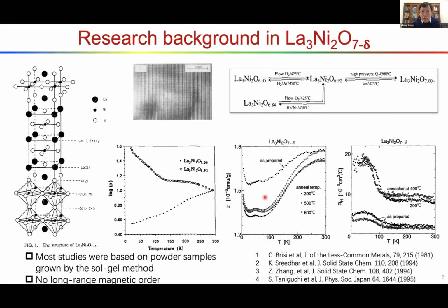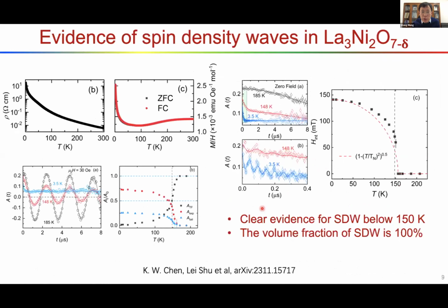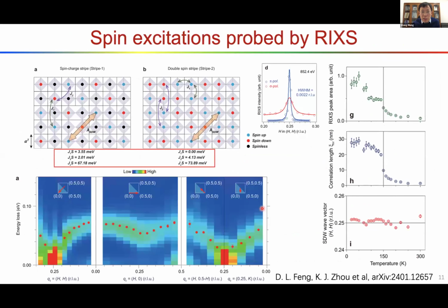People use this sol-gel method to grow thin crystals. Using this method, we can get powder samples with fewer oxygen vacancies. And actually, Professor Jin Changqing's group observed superconductivity on those samples. Yeah, but I'm just wondering whether the bulk susceptibility versus temperature still looks like what these old data look like. If we measure the sample at ambient pressure, it's very similar. But at high pressure, we don't know. Jin's group can only measure the sample below 15 gigapascal. But in this region, they couldn't observe superconductivity from susceptibility measurement.